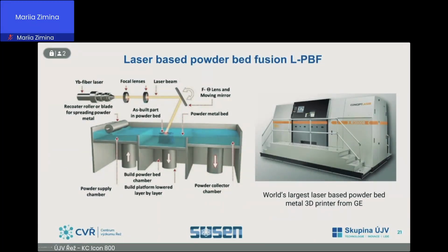Technology deficiencies: the process is limited by size, which limits the size of a part to approximately 35 kilograms. The deposition rate is relatively low, approximately 0.2 to 1.4 kilograms per hour. Assemblies may contain cavities, entrapped powder or fusion defects, and NDT inspection of thicker parts and complex geometries can be a problem.